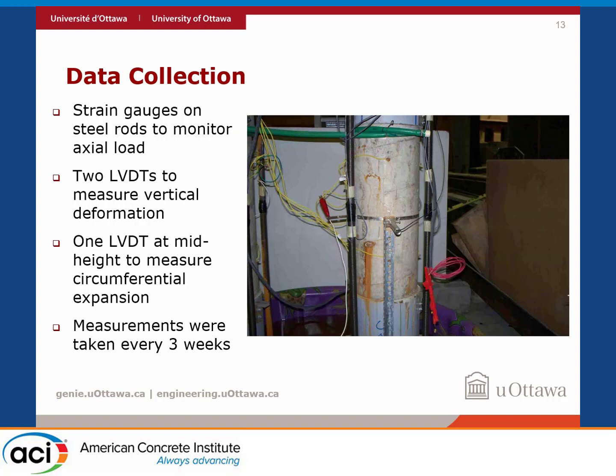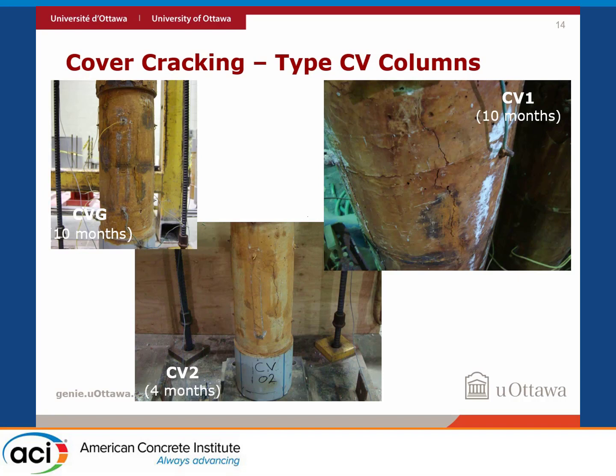We also had strain gauges at the steel rods that were applying the sustained load. One LVDT at mid-height of the column measured the circumferential expansion. And then we were taking measurements every 3 weeks for the period of 4 months or 10 months, depending on the column. So this is the cracking after the period for each of the columns.